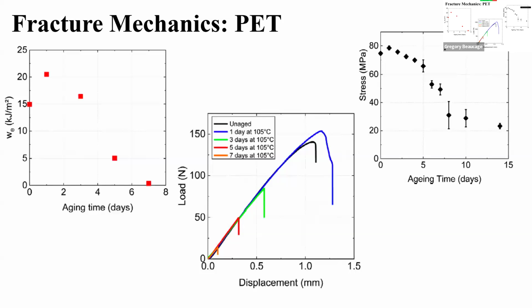So you can take that essential work of fracture, which is the amount of energy you need to run a crack through, and plot that as a function of aging time on the left. That's the red points. And what do you see? You find that it goes to 0 at 7 days. At 105C, that's when I started making micro nanoplastic. So it tells me whatever I'm doing to break bonds, at 7 days the sample becomes so fragile that a crack runs through spontaneously with no energy. And that's the point at which I make micro nanoplastic.